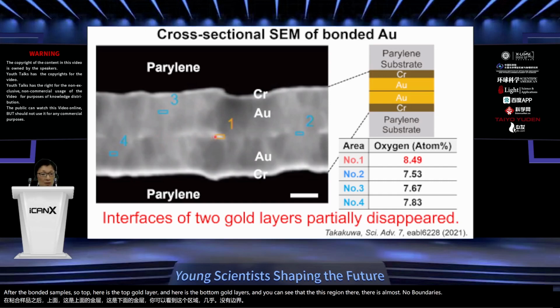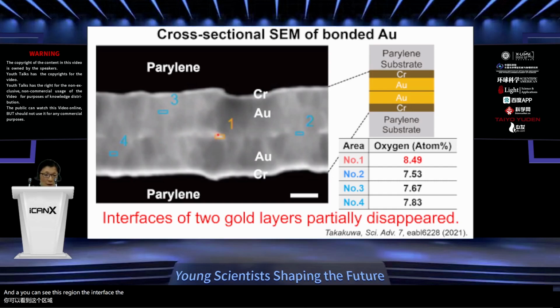And here is the cross-sectional SEM image of the bonded samples. Here is the top gold layer, and here is the bottom gold layer. You can see that in this region there are almost no boundaries. You can see the interface in this region or this region, but mostly such interfaces have almost disappeared. So this cross-sectional SEM image clearly shows we can make perfect gold bonding by using such simple water vapor plasma treatment technologies.